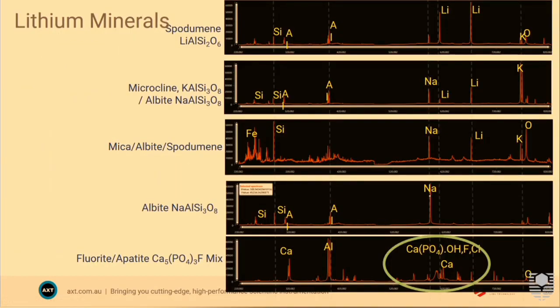This is some classic spectra. So looking at spodumene at the top, spodumene, lithium industry, can't analyse it by any other technique, so it's actually very good timing for this technology to come out because there's nothing else. Well, X-ray technology can't analyse for lithium. Yes, you've got ICP-OES and AAS, but you need to dissolve the sample. So you can see two very strong peaks for lithium. There's an oxygen peak.